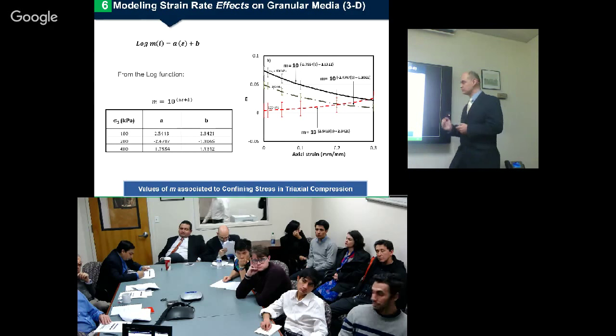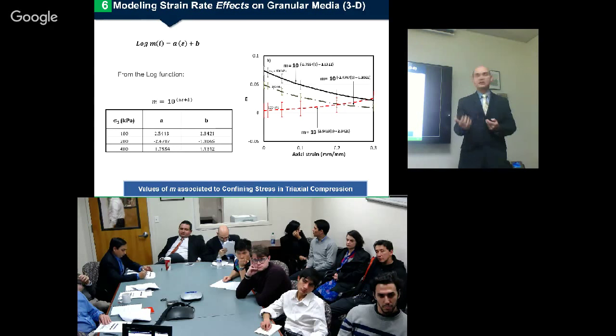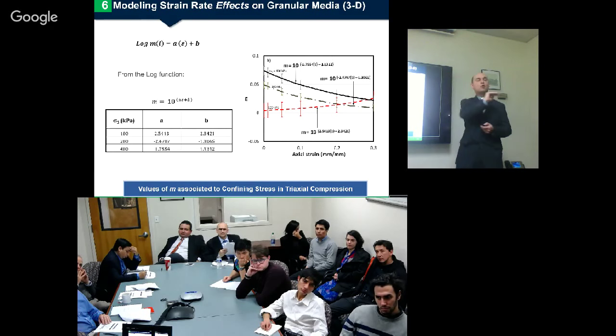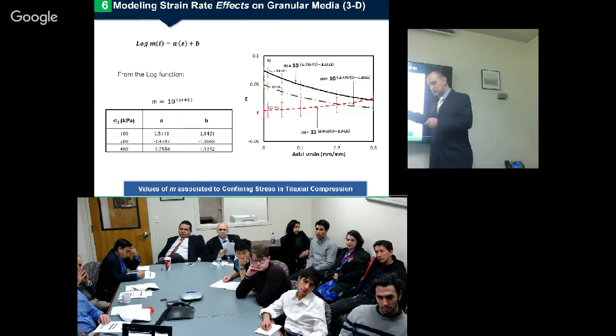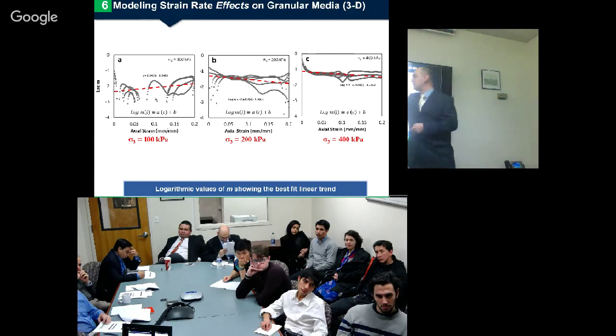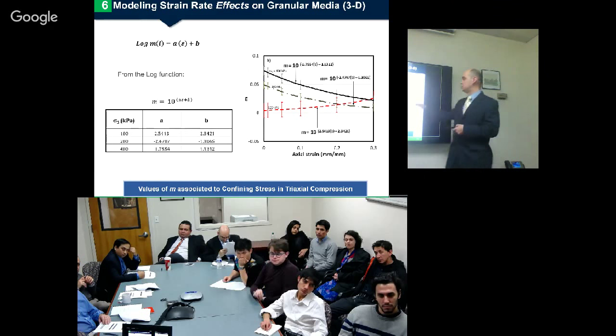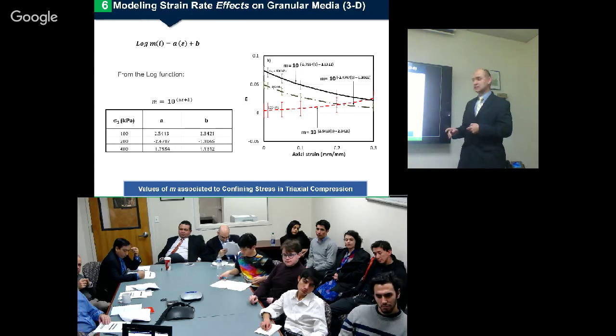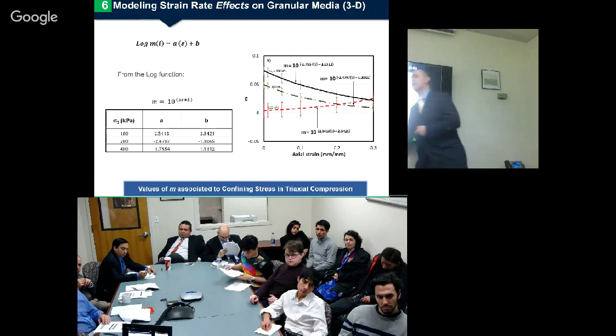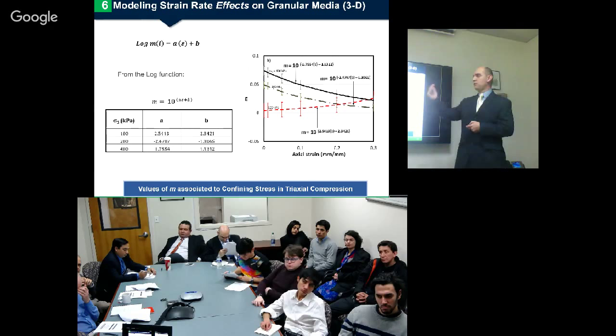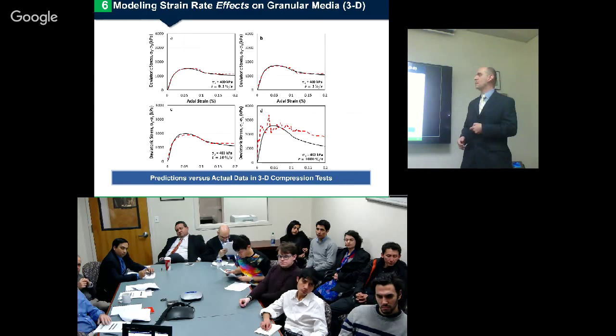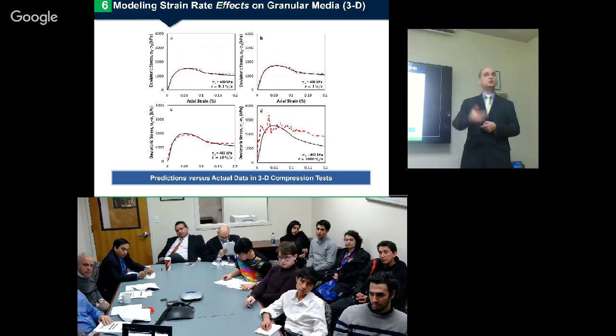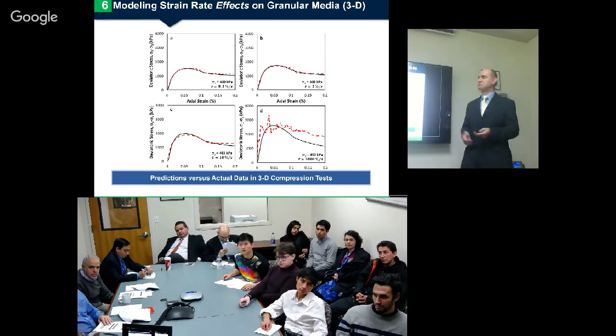with no rate effects, or conditions that don't provide rate effects, this line should be a horizontal line. Obviously this is based on all of these experimental results, but ideally it should be a horizontal line in this case. And now I got these A and B constant values for 3 different conditions of confinement. I go back and see I only plot here 400 kPa because for 100 and 200 there's not much of a rate effect.